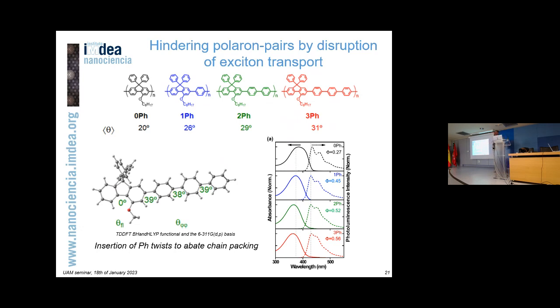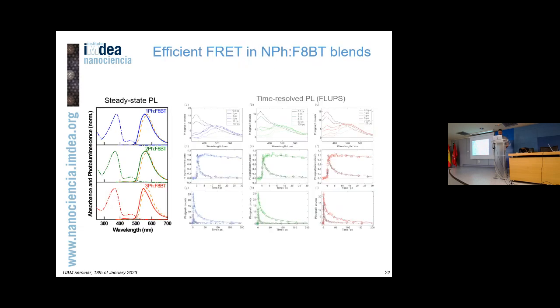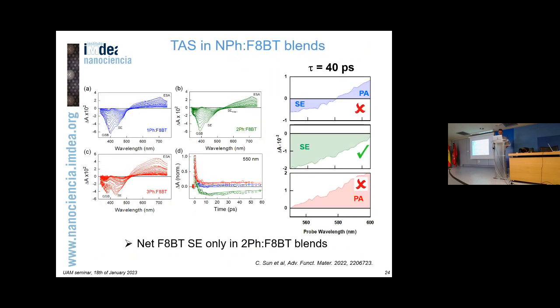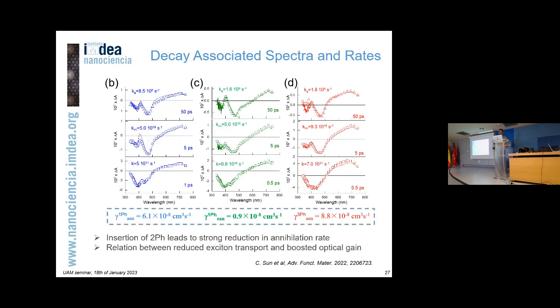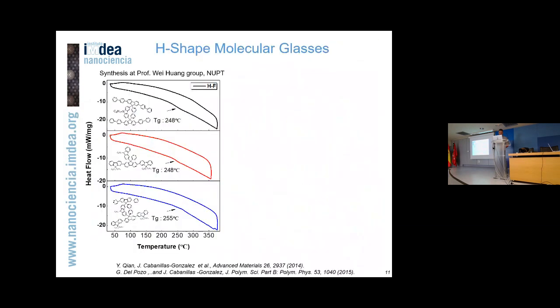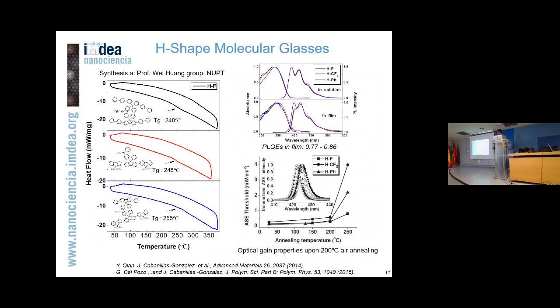Yet, in general, polymers are quite unstable. Molecules are much more stable. So the ones that I showed you after, they are really stable. We pump them in air, and we even anneal them up to 200 degrees, just to check the stability, the thermodynamic stability. So polymers tend to be more unstable, but you can devise materials that are quite more photostable.